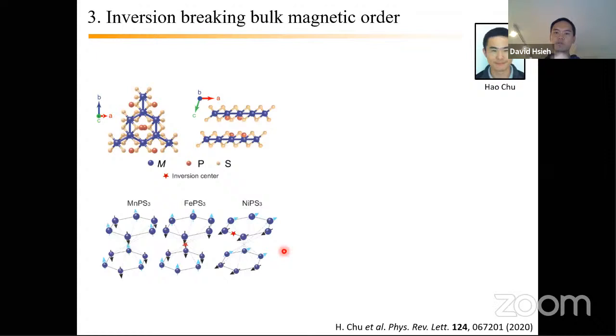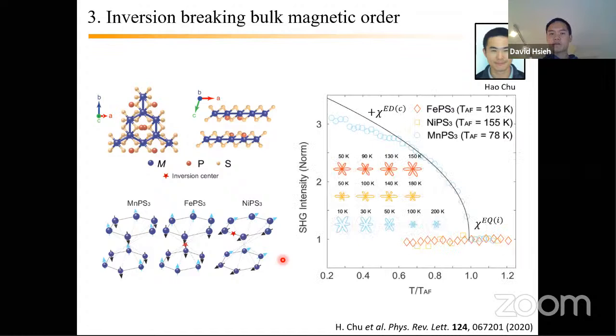An example we've recently looked at are these van der Waals magnets of ABX3 structure. I talk about this just to illustrate this point experimentally. So here, I'm looking at three materials, manganese, iron, and nickel phosphorus sulfide. The structure of these materials is the same, but the magnetic orders are different. In particular, manganese phosphorus sulfide breaks inversion symmetry by virtue of the Neel ordering of its spins, whereas the iron and nickel analogs have this so-called zigzag antiferromagnetic structure that preserves inversion symmetry. And so if you do SHG on all of these, what you find is that in the nickel and iron cases, there's really no feature across the magnetic ordering transition, whereas there's this huge jump in the manganese version. That's exactly emblematic of the fact that it breaks inversion.